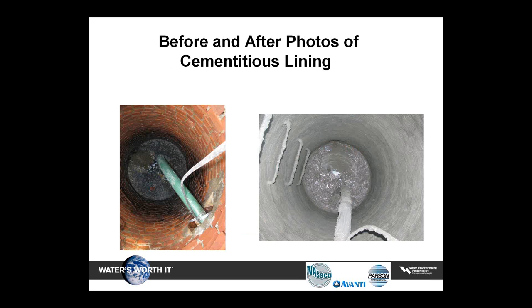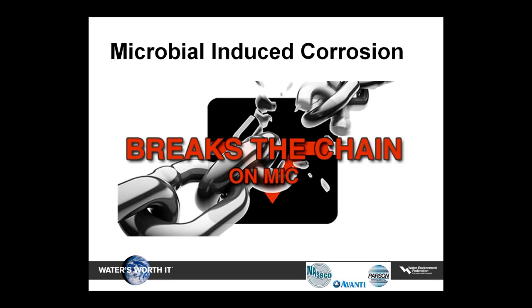100% pure fused calcium aluminate cement with calcium aluminate aggregate products arguably have the highest resistance to corrosion due to the addition of calcium aluminate aggregate, which is much harder than sand. The product has similar working time characteristics to calcium aluminate. There are only several manufacturers that can provide this type of product, however, as calcium aluminate aggregate is difficult to obtain.